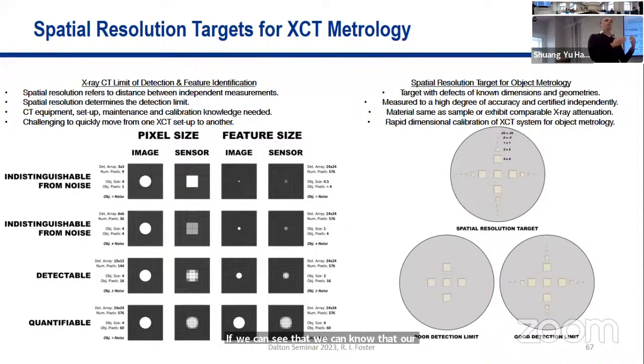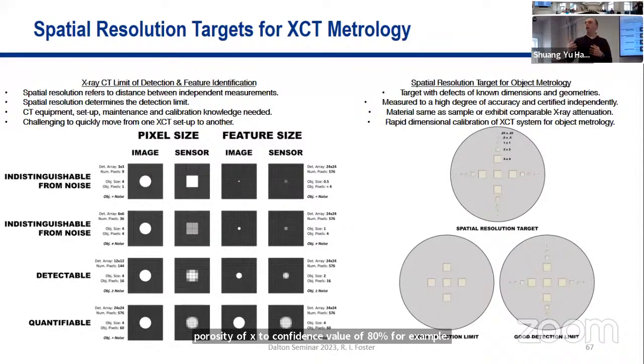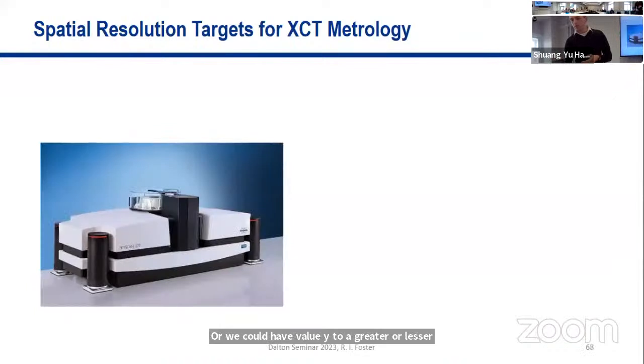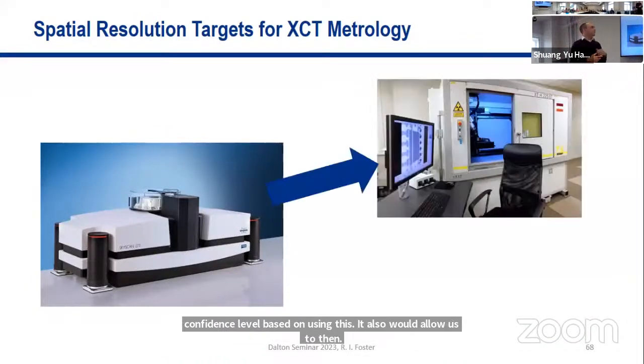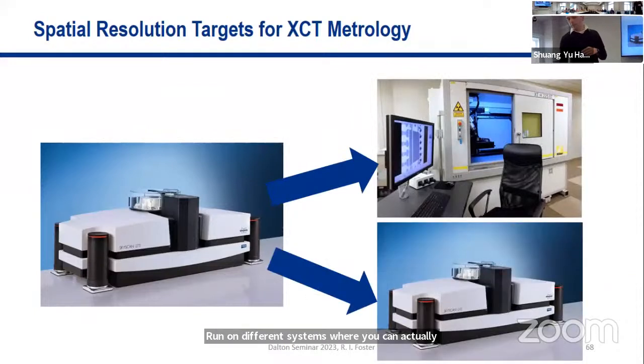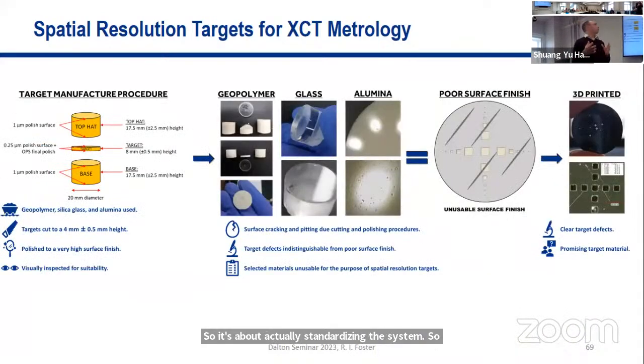Likewise, if we don't see it, we can confidently say and have a greater confidence in our measure that that object cannot be seen. We can then rerun our final samples, our actual waste forms, and then calibrate and say, yes, this has a porosity of X to a confidence value of 80%, for example. Or we could have value Y to a greater or lesser confidence level based on using these targets. It also would allow us to then run on different systems where you can actually calibrate across, or use the same system on a different day or a different person. So it's about actually standardizing the system so we can get confidence throughout the process.